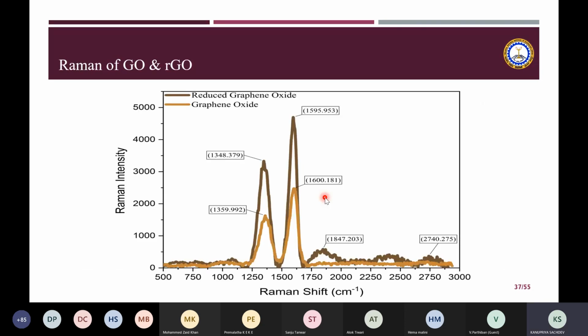This is the Raman spectrum, and this gives you the Raman spectrum of both the graphene oxide and the reduced graphene oxide. So we see that the ID by IG ratio varies when you move from graphene oxide to the reduced one. In the case of the reduced one, because the functional groups are less, that leads to better hybridization of carbon, but at the same time, it may cause some defects also. So there is always a variation in the ID by IG ratio when you go from graphene oxide to reduced graphene oxide.